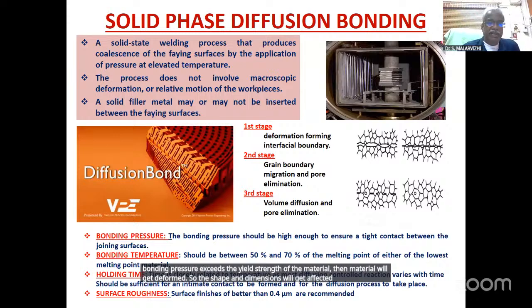And bonding temperature, again, the bonding temperature should be 50 to 70% of the melting point, because you should not go to very high temperature either, because that leads to recrystallization and other problems will come. So it should be below the recrystallization temperature.